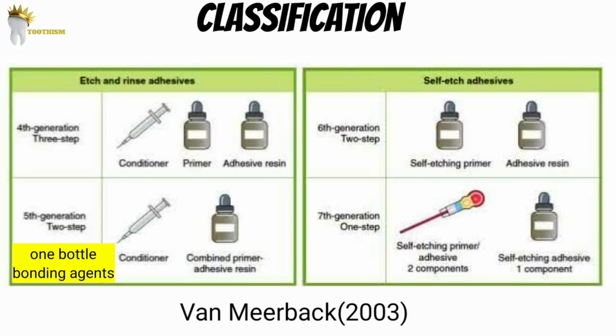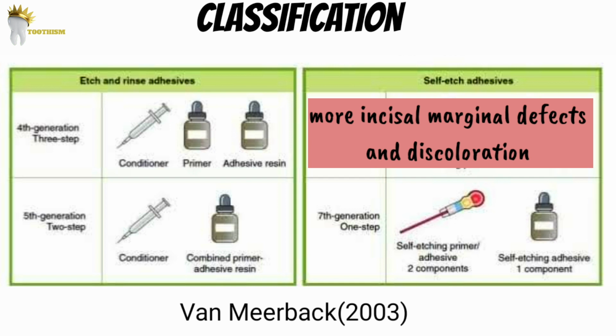Recently, a randomized clinical trial showed that one-step self-etch adhesives had similar clinical performance after 3 years compared with that of an etch and rinse adhesives in class 5 restorations. However, the one-step group exhibited more incisal marginal defects and discoloration compared with the etch and rinse group.